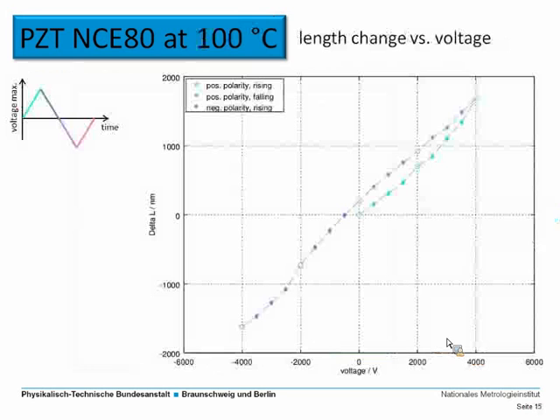Okay, then let's do something more interesting. Let's go to higher temperatures. In this case, 100 degrees centigrade. It's the same sample, the same measurement scheme as before, just at a higher temperature. So again, this is the length change plotted as a function of voltage. We start from 0, go up, go back down to negative polarity, and in principle back up again. And already here you can see in the positive polarity part something like hysteresis behavior.